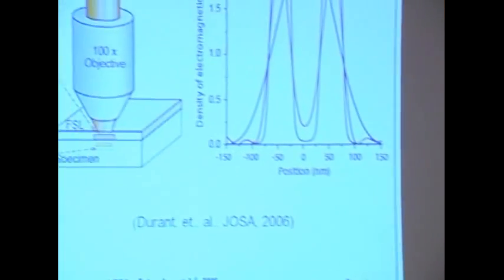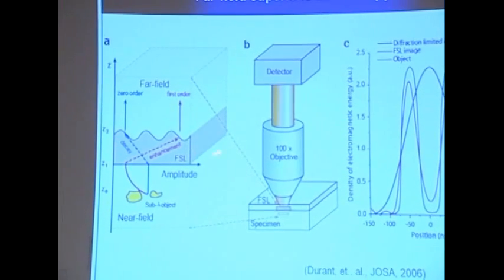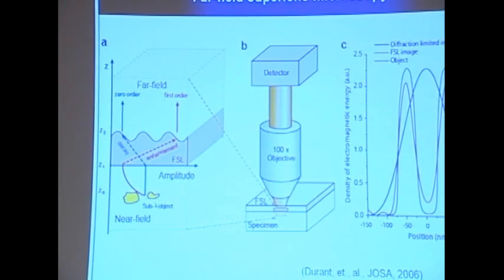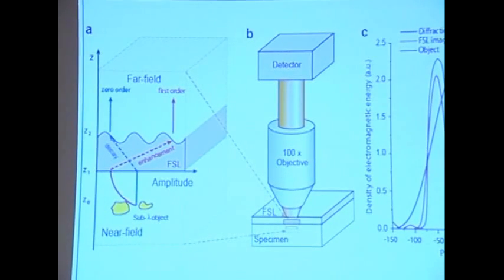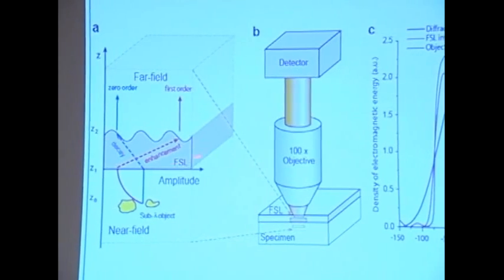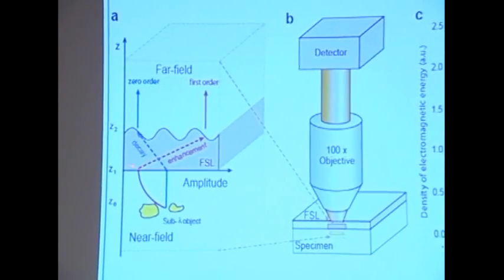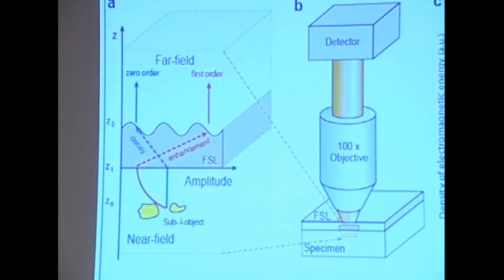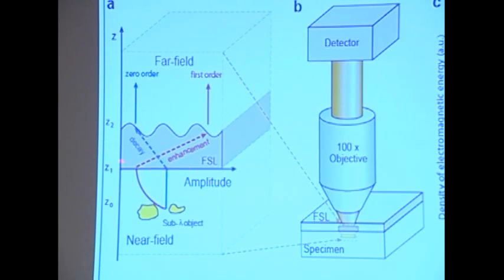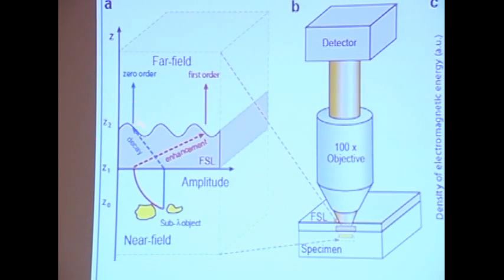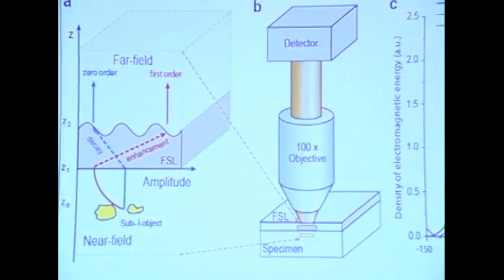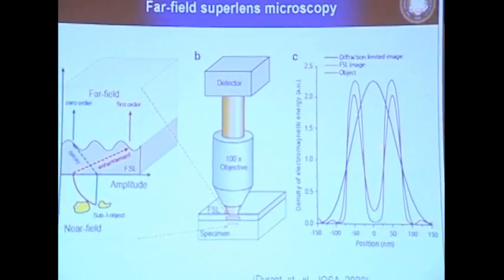So if we can construct a nanoscope for optics, that would be very interesting. One of the methods we pursue is using surface corrugations together with surface plasmon excitation. Previously we introduced this flat slab of silver. Now you put surface scatters, whether one-dimensional or two-dimensional, and you design these surface scatters very carefully. This far-field optical superlens has two functions. First of all, it will enhance this very large k-vector wave, the so-called evanescent wave, the same function we discussed for the superlens before. But once the amplitude is enlarged, you use these surface scatters to convert this evanescent wave to a propagating wave. That is the basic idea. Then everything else can be integrated with a regular optical microscope, but you can achieve imaging at the nanoscale.